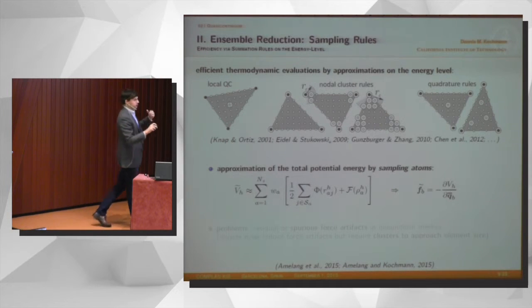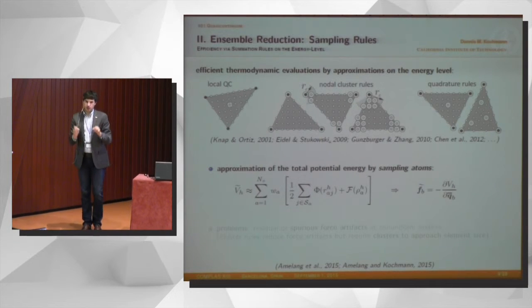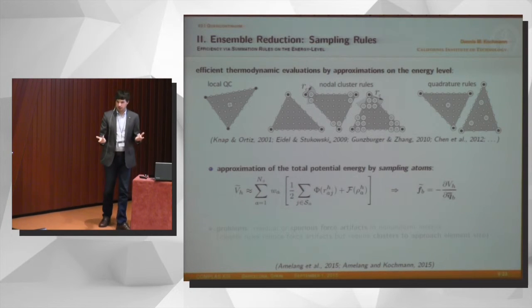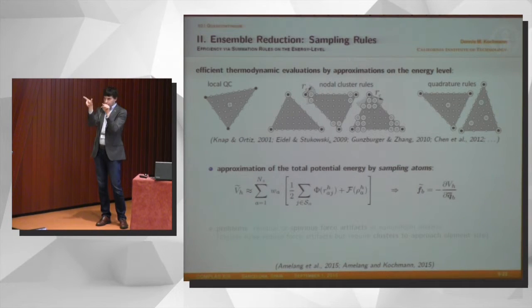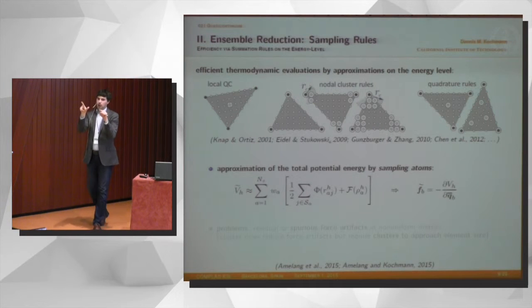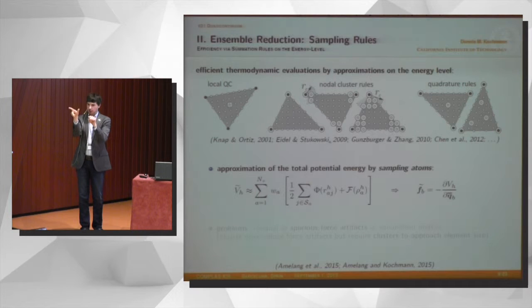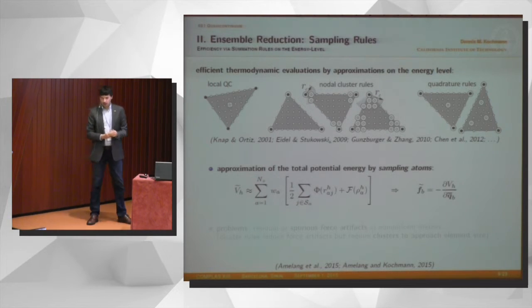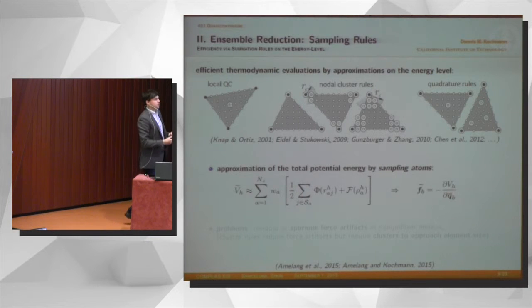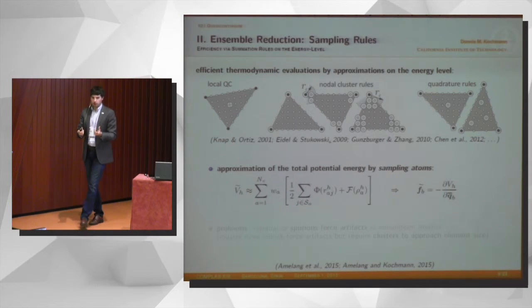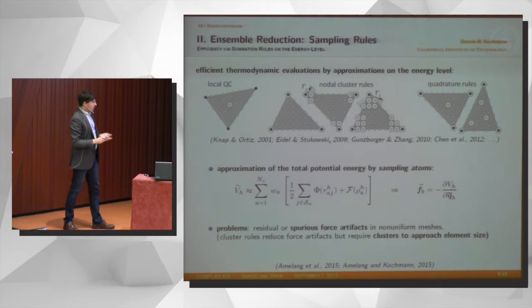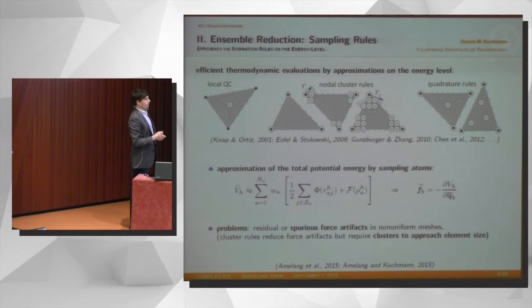But this error, this mistake that you're making also manifests itself in the forces. If I now compute the forces on these representative atoms, they will not be exact because I made a mistake. I'm only considering the energy of a few atoms and not of all of them. Now what can happen is you can artificially find states where these 4 atoms have lower energy, but all the others have very much higher energy. This is an artifact, and so what this means is that the system can actually see forces which are absolutely not physical. And these are called spurious forces or residual forces.